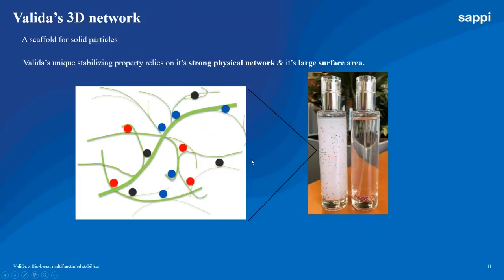Here in this picture on the right, a proof of concept on the stabilization potential of Valida. When suspended in water, Valida builds a network, which will prevent suspended particles from falling down or sedimenting and separating over time. For example, here we have the jar only with water and here with Valida. The viscosity of the container containing Valida is not much higher than the water itself, but you can see how incredibly stable the particles are in the formulation, and this is basically due to the action of the 3D network and the surface area. The 3D network basically acts as a scaffold for these particles.